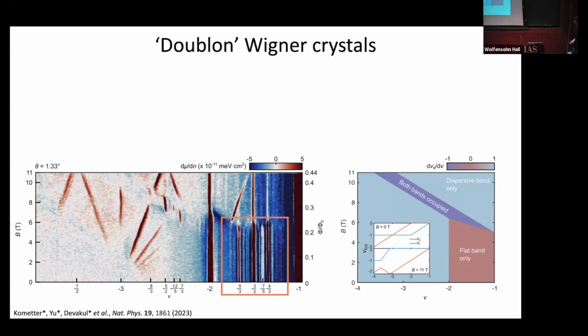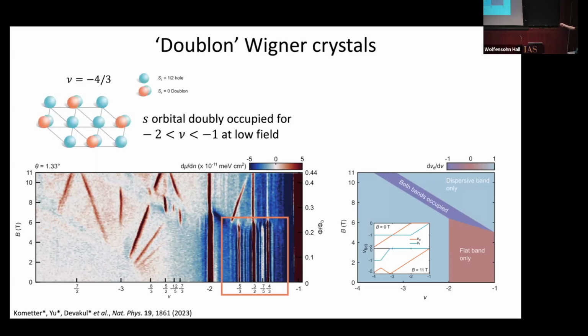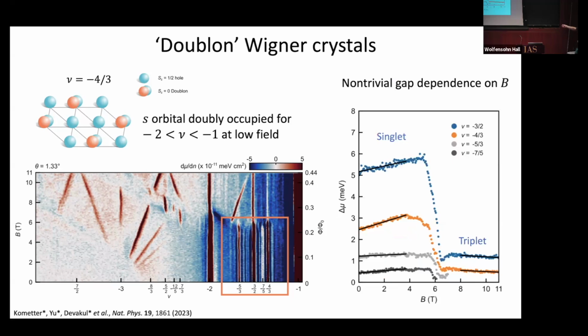I'll also point out that there's something kind of cool here. As you go up in magnetic field in this lower region, down here, you've doubly occupied the same orbital. So these form doubly occupied sites, doublons, which are singlets in this low magnetic field regime. But in the higher magnetic field regime, actually, they're triplets. That is, you have s orbitals and p orbitals of the same spin type, again occupying the same site. We can extract the energy gaps across this transition of different generalized Wigner crystal states. And you can see there's a dramatic softening as you occupy the more dispersive bands and form this triplet state. But in some sense, this is similar to a singlet-triplet transition in a quantum dot system.